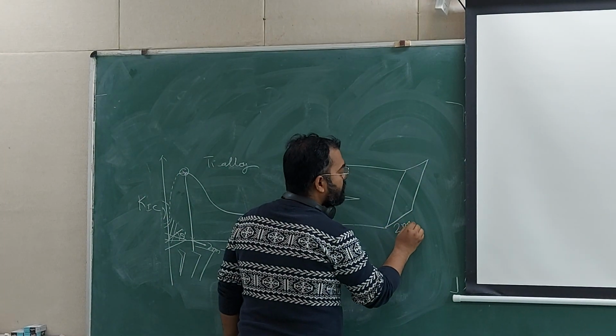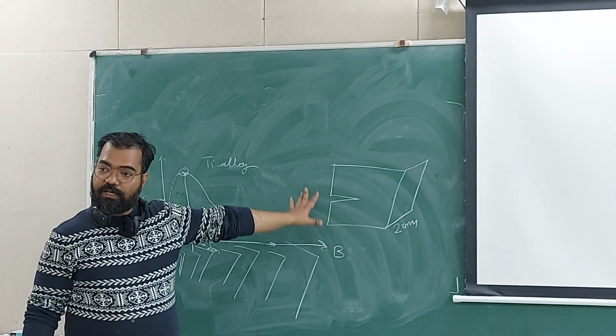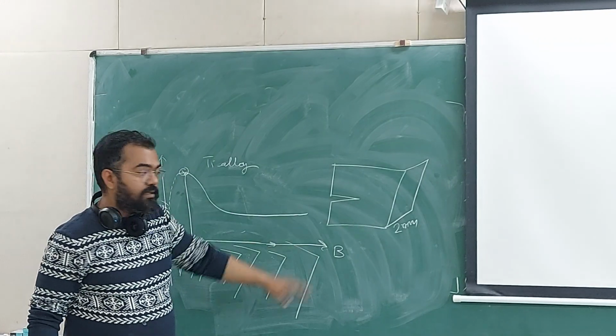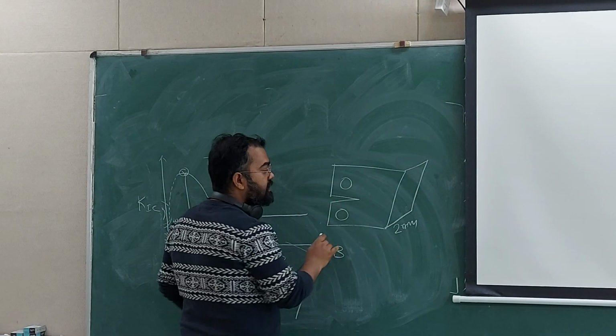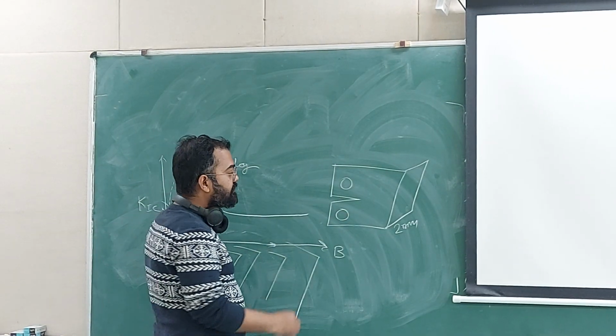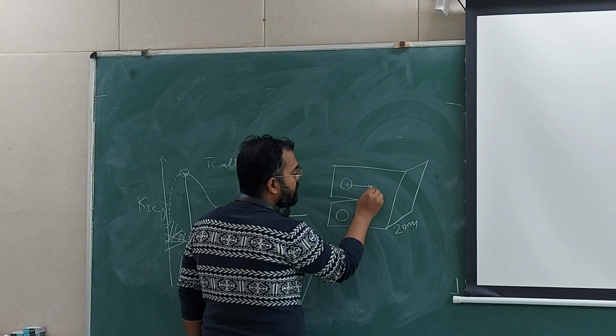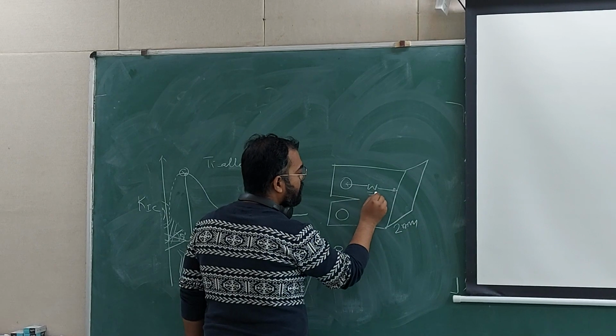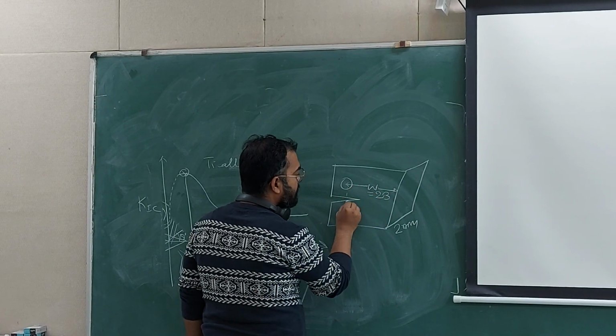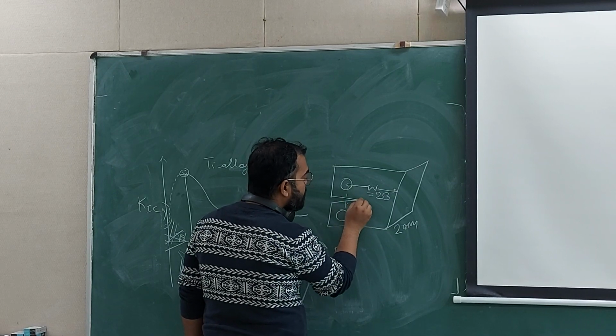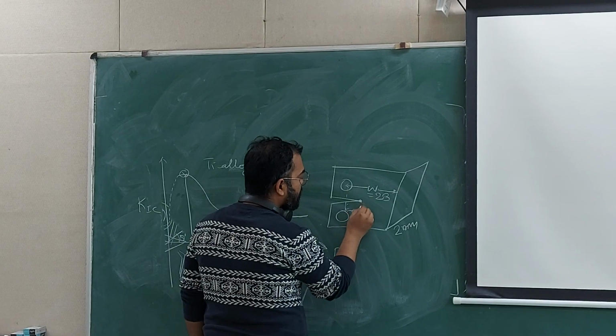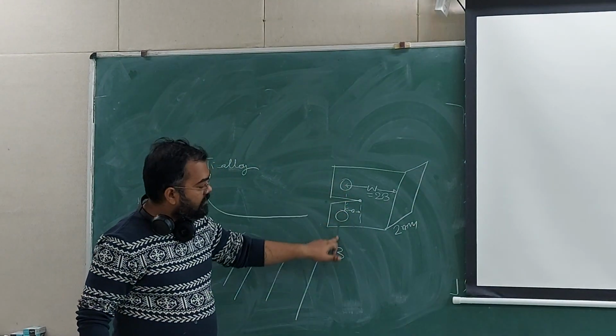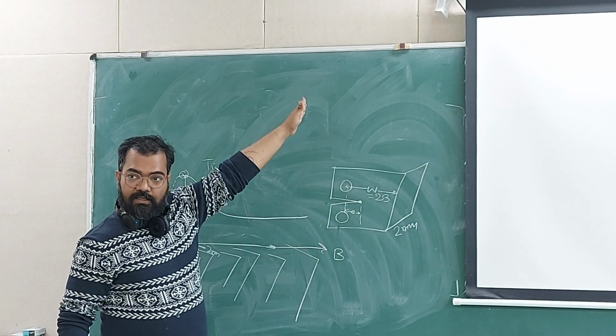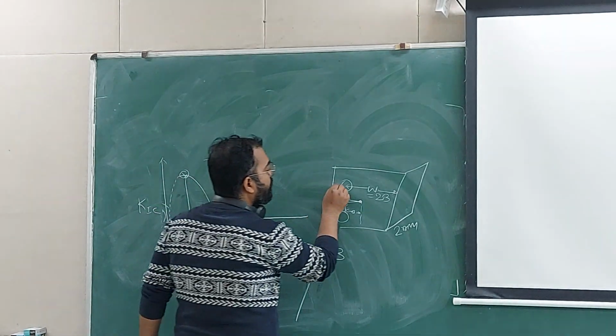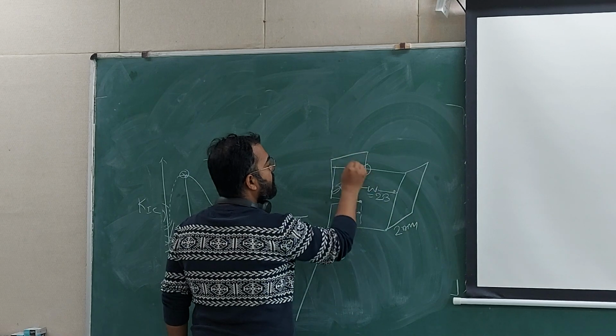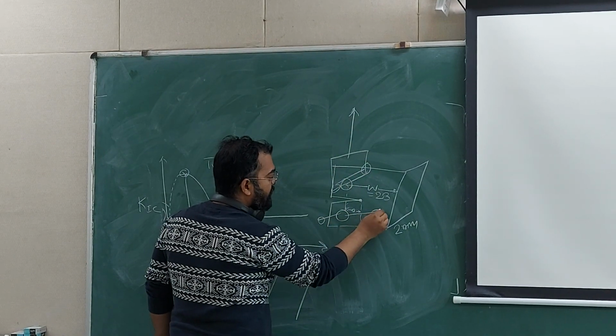If my specimen thickness was 2 millimeter, all other dimensions will scale according to thickness and crack length as per standard. Usually you use this kind of specimen. I'll discuss in detail later how to do the test. This is known as the width of the specimen, which is usually 2 times the thickness, and this is the crack tip, and this distance is called the crack length of the specimen, measured not from here but from there, because that will be aligned in the testing machine. You will have pins here, and these pins will be connected with the machine, and the machine will be pulling this pin up, and this pin will remain fixed.